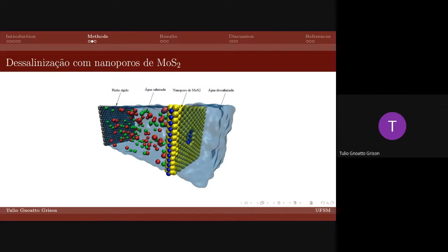A nanopore was made by removing the designated atoms, with perforations ranging from 20 to 60 angstroms in area. The system contains around 16,000 atoms.